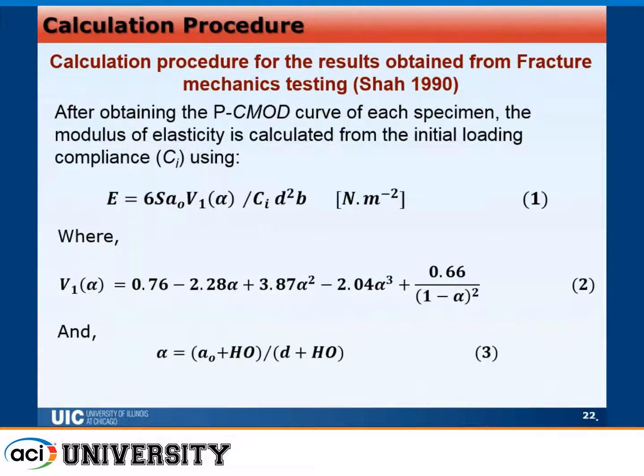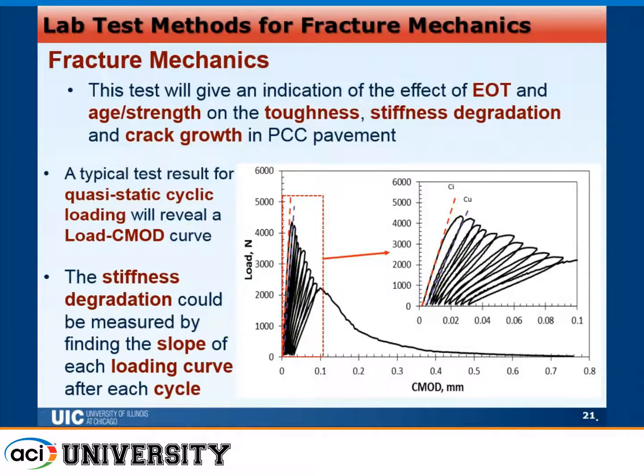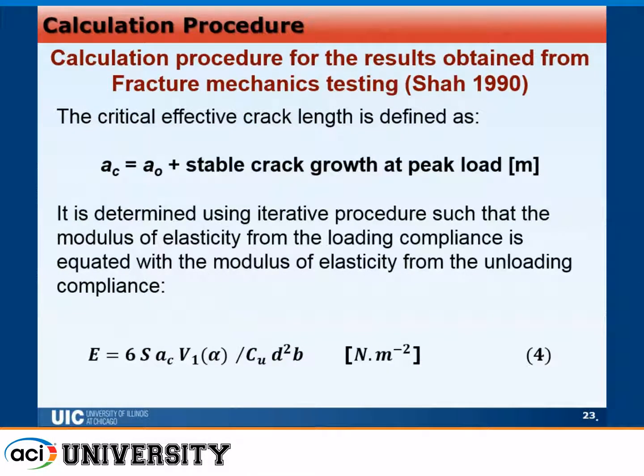These are the equations from the literature used to calculate the parameters. The purpose is to equate the compliance factor with the unloading compliance and the loading compliance obtained from the CMOD, as you see in here. Once you equate them, you will have a critical stable crack growth.